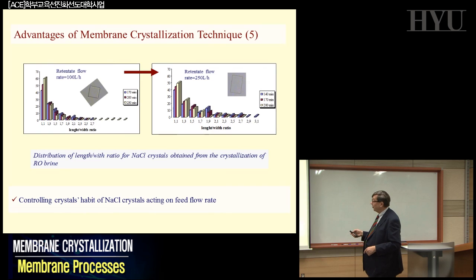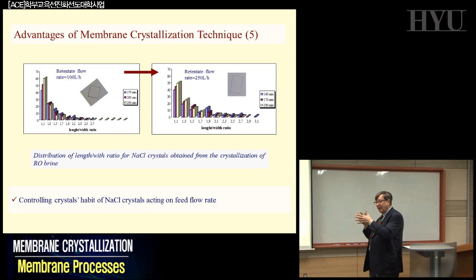This is an interesting slide, because look here, if you change the axial flow rate, the retentate flow rate, this is 100 liters per hour, this is 250 liters per hour, so you are just changing the speed at which your molecules are running on the membrane surface, you can see what is happening. This is at low speed, this is the form of your sodium chloride, if I remember. This is when you are increasing. As you can see, you have elongation, which is what you expect. You're just inducing, it is much easier, the molecules to interact with each other. If you are increasing the axial flow rate, that is the one that is coming out compared to what was coming out here. And now you can extrapolate this kind of phenomena.